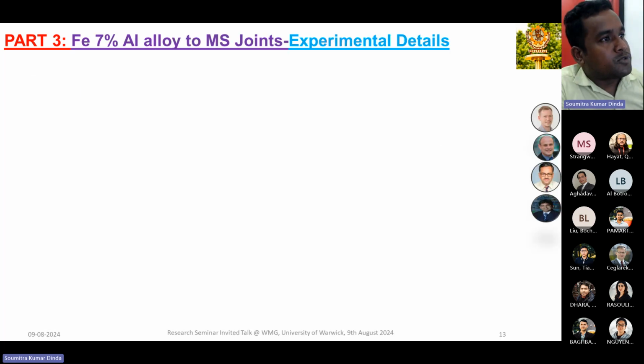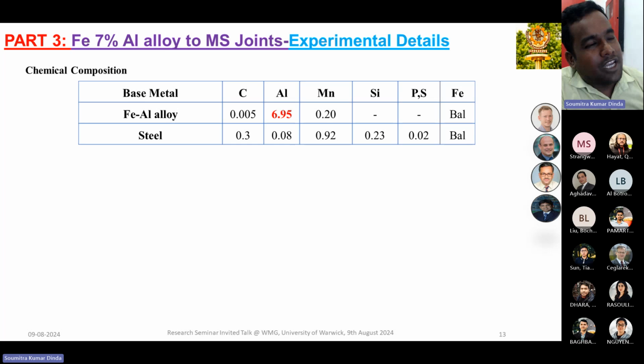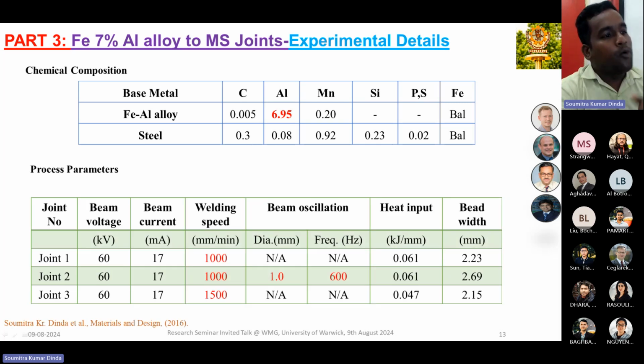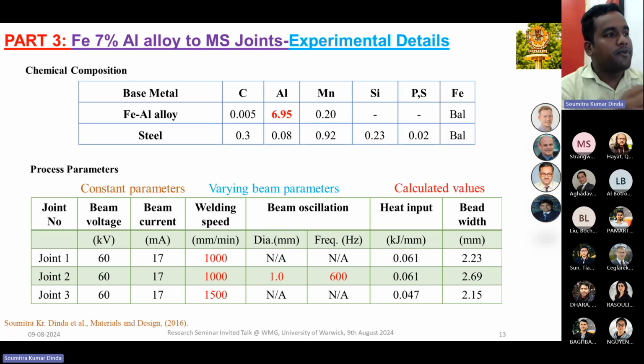So in terms of experimental conditions, this is the chemical composition of both materials. The FeAl alloy has an aluminum percentage of near about 7%, and this is the normal mild steel with a maximum carbon percentage of 0.3%. And this is our processing condition. If we divide this processing condition in three ways: constant parameters, varying parameters, and calculated values. The constant parameters are the beam voltage and beam current, which we keep fixed for every condition. The varying beam parameters are the welding speed and the beam oscillation.